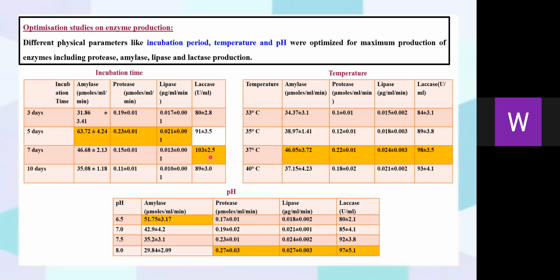Optimization studies: incubation period, temperature, and pH were optimized. In case of incubation time, amylase, protease, and lipase show maximum enzyme production at 5 days, and laccase shows maximum on the 7th day. Temperature: 37 degrees was found to be the best temperature for maximum production of all four enzymes. pH 6.5 is the optimum pH for amylase production, whereas pH 8 was found to be the optimum for protease, lipase, and laccase.